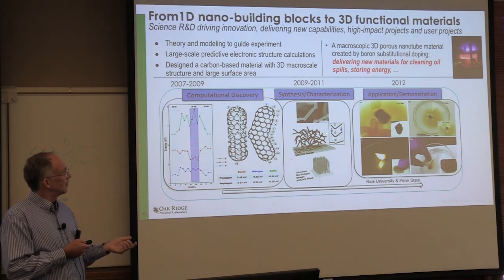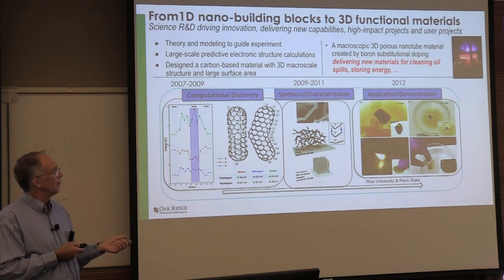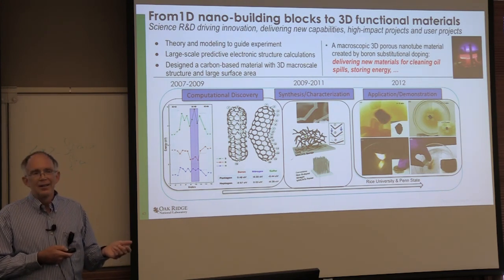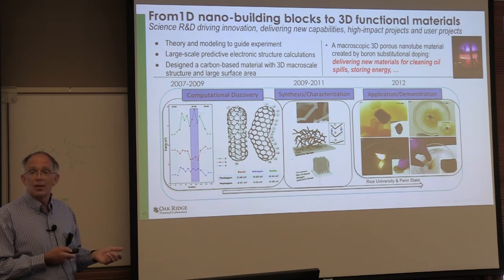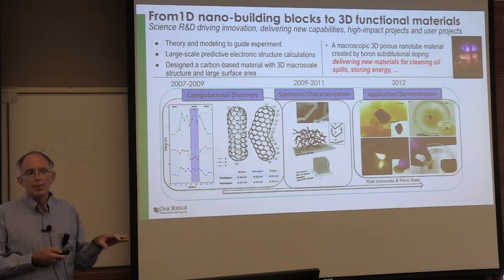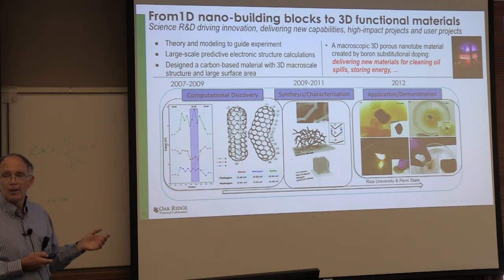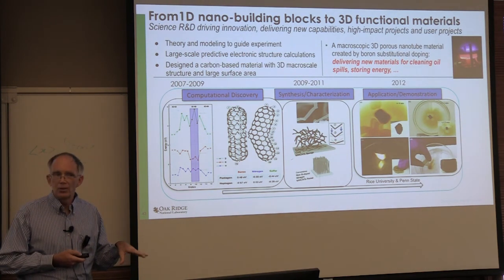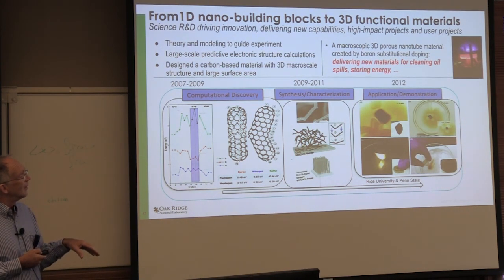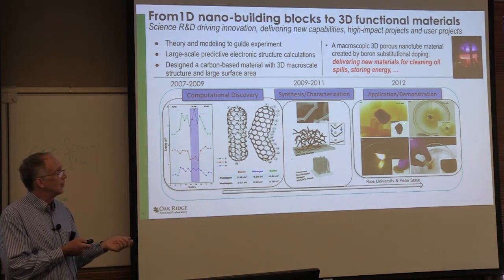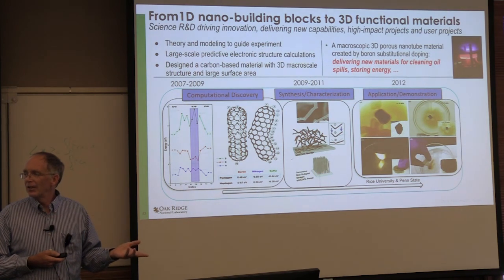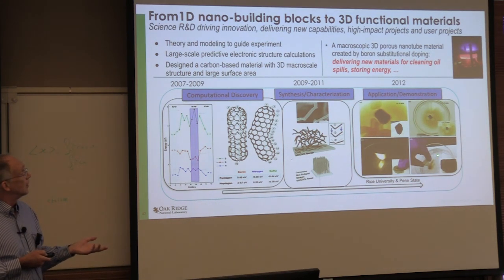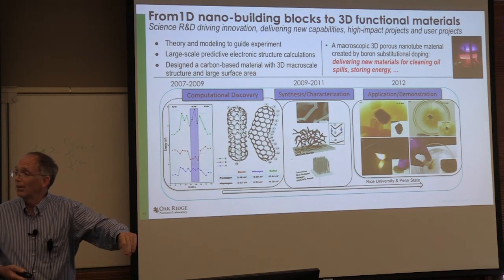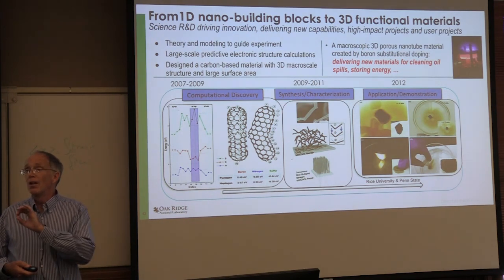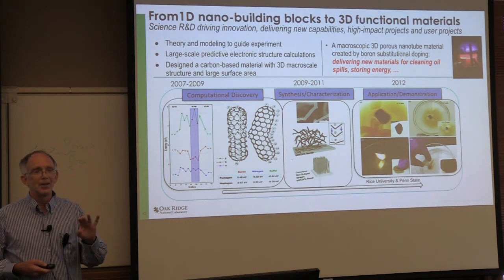Couldn't that thing, since it's supposed to act like a sponge, just soak up that oil? And, well, yeah, it can. You just drop it in there. It won't soak up any water because it's hydrophobic. It's actually super hydrophobic. If you measure the contact angle, it's huge. So it selectively will soak up oleophilic type systems, including oil, in a complicated solution like seawater. And then you can just squeeze it out like a sponge, recapture the entire oil, pure oil, no seawater in it because it's super hydrophobic.